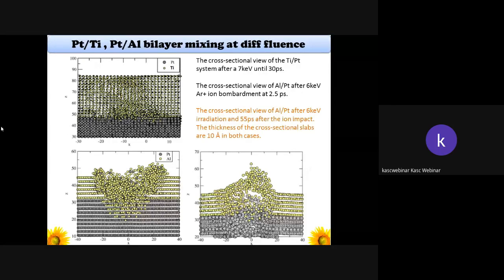These are a few examples of bilayer mixing cases. The first diagram clearly indicates the bilayer of Pt and Ti, and the second and third represent the bilayer of Pt and aluminum. Actually, the cross-sectional view of a Ti-Pt system, after 7 keV of energy deposited over the sample until 30 picoseconds, we may expect only a little bit of interface mixing. Again, the next system was irradiated with a 6 keV argon ion bombardment, but the time of exposure was changed from 30 picoseconds to 2.5 picoseconds. Then at last, the cross-sectional view of an aluminum-Pt layer after 6 keV irradiation and 55 picoseconds of ion impact. The thickness of the cross-sectional slabs is 10 angstrom in all the cases.